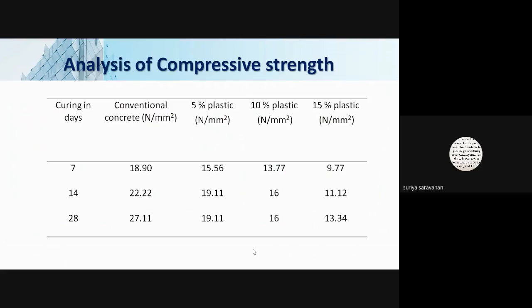And the analysis is that, for 7 days curing, conventional concrete gives 18.9. If you replace it with 5% plastic, you can see 15.56, at 10% it is 13.77, and at 15% it is 9.77. So it shows that there is a decrease in compressive strength. Even for 14 days curing, we can see that for 5% plastic the compressive strength is 19.11, for 10% it is 16, and for 15% it is 11.12. So we can see a decreasing trend of compressive strength.